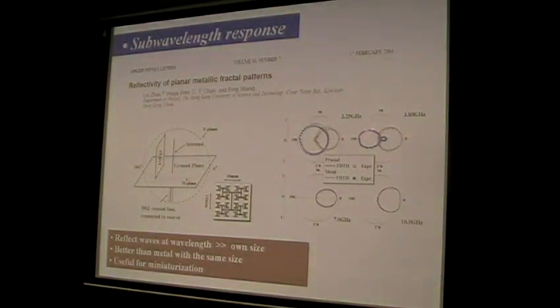You can see that at these two frequencies, which are lower frequencies, the radiation is actually not blocked. And even more interesting, we find that the radiation along this direction is even higher than along this direction. So that means a metal plate cannot block the EM wave at all. However, if you replace the metallic plate by a six-level fractal plate of the same size, you find at this particular frequency, it can reflect the EM wave very efficiently. This is the radiation pattern given by the fractal plate, and you can find it can reflect the EM wave very efficiently.